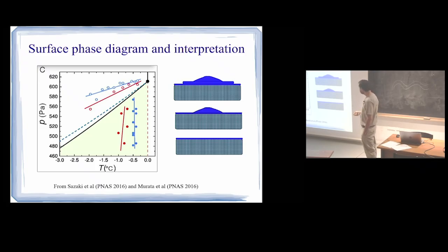The matter of fact is they do see that eventually when you cross this red line, you get droplets. And there is one curious thing here occurring. The droplets only appear well above the saturation of the metastable prolongation of the liquid-vapor line. Droplets typically you would expect to appear right there, but actually they appear at a much higher saturation. Okay? And then eventually, if they cross this blue line, they get the instabilities. Okay? This state.